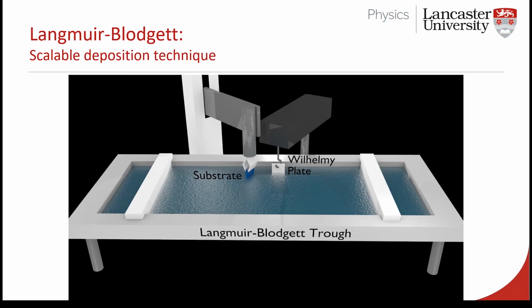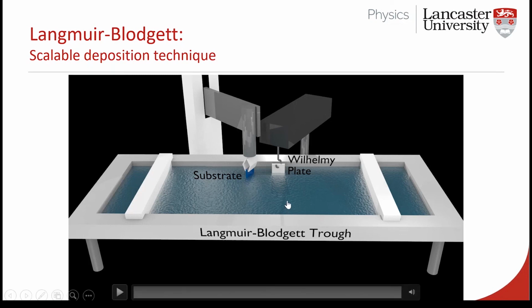So for Langmuir-Blodgett deposition, we have our surface, we have our material. You've made whatever it is you want, and you want to coat it. You want to put some functional coating on there, either to protect it against the outside world, so that might be for antimicrobial applications, it might be to make it hydrophobic, or it might be to promote adhesion to the next layer that's going on there. One of the ways that we can put a very thin film, a single molecular thick film, on there is using this technique of Langmuir-Blodgett deposition.